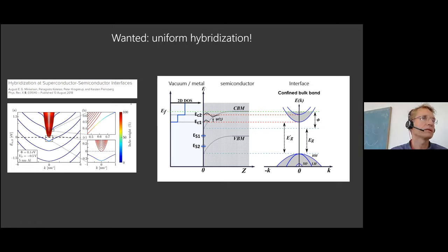when you take a semiconductor, in this case 100 nanometers of indium arsenide together with 5 nanometers of aluminum, then you get something like this, where in this really ideal case, you see these quantum well states with large level separation. You have this energy scale of electron volts on the side. In principle, you will break up the bands of the aluminum, and you can also see level separations in the indium arsenide. And then the coupling takes place typically around the Fermi level.